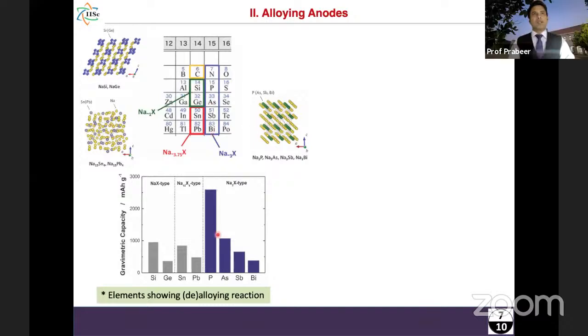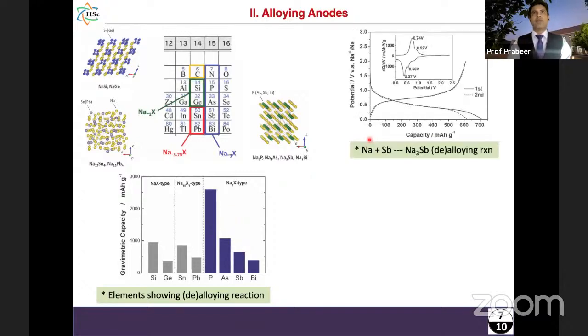So if we see this diagram here, particularly for silicon and germanium, the capacity is not so good, but when we go to this NaX kind of material, particularly with phosphorus, we can give rise to very, very high capacity, over 2500 milliamp per gram. And with this, it is possible to design different kinds of alloying-based anode material. I want to give you two examples. One is with antimony, one is with phosphorus. So the first one is with antimony.